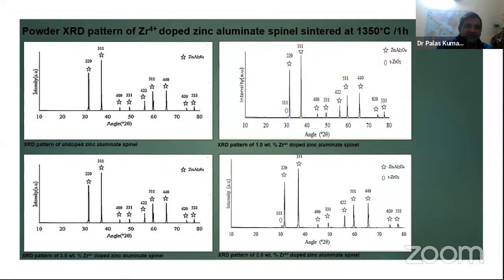next, coming to the XRD study of the zirconia doped zinc aluminate spinel at 1350 degrees centigrade. It is very clear that from dopant concentration 1 and above, there is basically found the secondary phase of tetragonal zirconia, and the peak is very small for 1, but for 2 the peak is more clear and sharper.